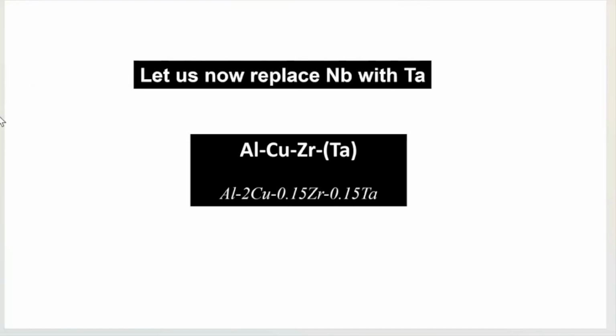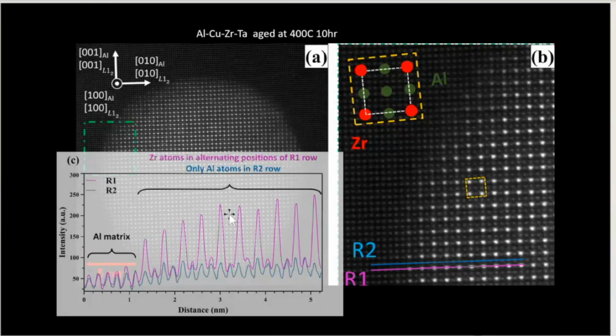Why tantalum? Because we thought that niobium and zirconium probably stop the segregations, because zirconium and niobium diffuse very slowly in the aluminum matrix. Therefore, these alloys do not coarsen. And we thought that if we add tantalum, that will be even slower. So probably we'll get a better effect with a small amount of tantalum. And Al3Ta also is an ordered precipitate. So we added 0.15 tantalum with 0.15 zirconium. And of course, with the addition of tantalum, it still produces the ordered phase.